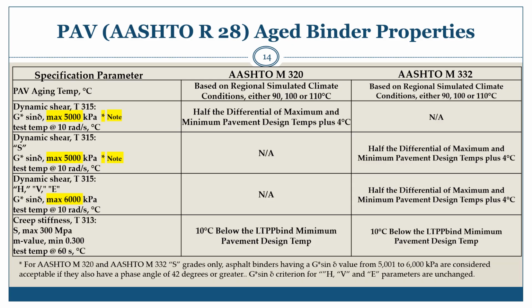M332 PAV aged specimens tested at specified intermediate grade temperatures for S grade binders are also limited by G-star times sine delta to a maximum of 5,000 kilopascals. Again, note that with M320, S grade binders that have G-star times sine delta values of 5,001 to 6,000 will be considered acceptable if they also have a phase angle of 42 degrees or greater. M332 PAV aged specimens tested at specified intermediate grade temperatures for H, V, and E grade binders are limited by G-star times sine delta to a maximum of 6,000 kilopascals.